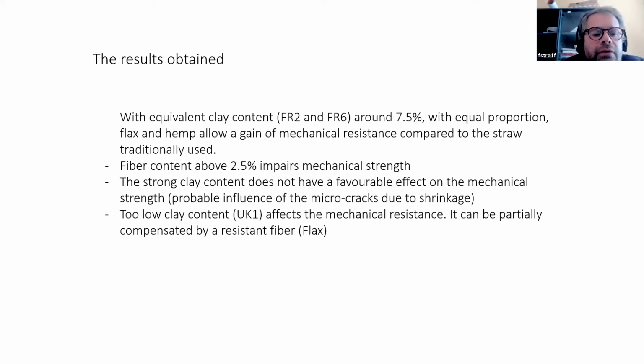A fiber content around 2.5% impairs mechanical strength. The strong clay has not really a huge impact on the compressive strength, and if we have finally a very low clay content soil, finally this experiment shows that just using a different fiber could allow us to improve a bit the compressive strengths of this poor material.